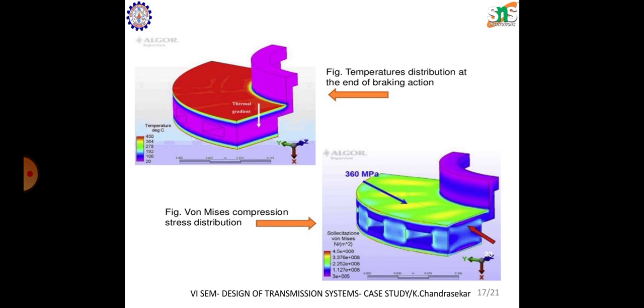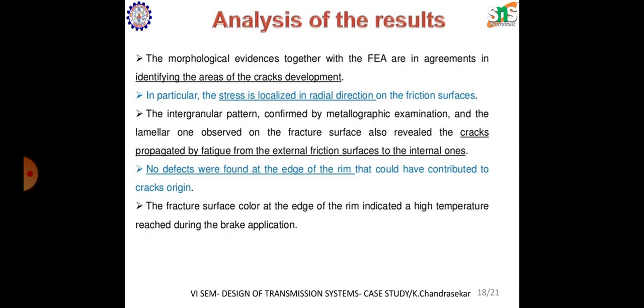The surface where the pads join with the disc has a very high temperature, and if we go to the inner side, the temperature reduces. The analysis view is shown here. The first picture represents the temperature distribution, and the second picture represents the von Mises stress distribution. Where the break appeared, the stress exceeds 360 megapascal. So the results are as follows.